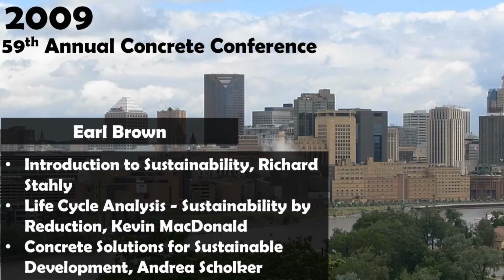Eventually we got down to a point where we had about 80 pounds of Portland cement, the remainder of that mixture being recycled material: slag, fly ash, recycled aggregates. And in exchange for the largesse of providing this steady concrete, Mr. Stahly said he would run a bunch of testing. And among those, rapid chloride permeability and shrinkage, which we had not looked at before because we were, to be frank, looking at mass concrete and temperature.